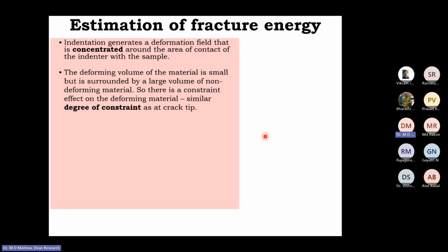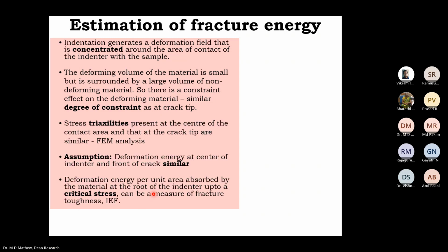For a crack to progress, it depends upon the kind of triaxiality at the crack tip as well as the kind of constraint that it is facing for the propagation of the crack. So a kind of equivalence is conceived in this case. It is assumed that the stress triaxialities at the center of the contact area of the indenter and the material are similar to those that exist at the crack tip. And this has been proved by other researchers through finite element analysis.